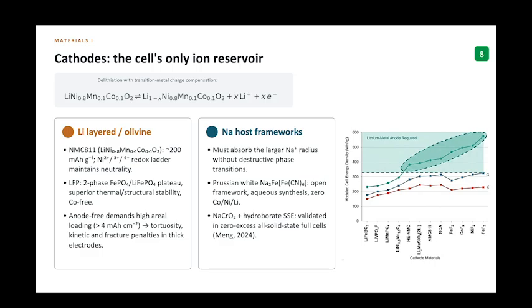Silicon lifts the ceiling into the low 300s, but swap in lithium metal, and the same cathode ladder runs from above 380 all the way up to the 600s. The fluoride cathodes that looked completely pointless with graphite quietly become the end game. So anode-free doesn't just delete dead weight.